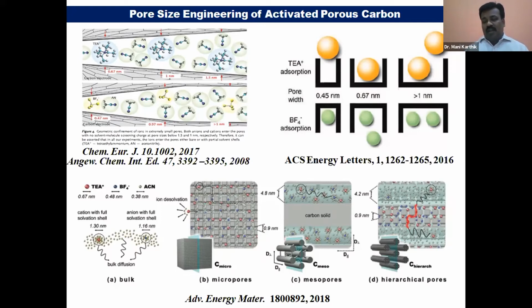But on the other hand, the ions are not going to penetrate into the pore. That's a problem. So the micropores contribute the surface area, and the mesopores contribute electrolyte diffusivity so that the ions can go to the micropores. This combination is called hierarchical pore structure. So a certain combination of micro and meso enhances the rate capability as well as the high performance of the supercapacitor.